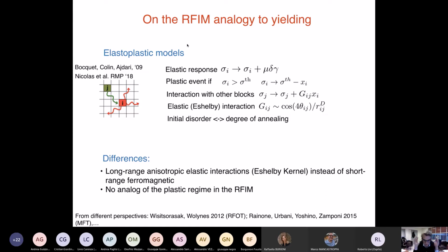Instead, if you equilibrate super quickly, then the system will be very disordered, and the local configuration will not optimize well either the steric constraint or the energetic constraint. So in this model, in order to put in the degree of disorder, which is related to the degree of annealing, we decide that the initial distribution of the sigma I can be a peaked distribution, or it can be a broad distribution.